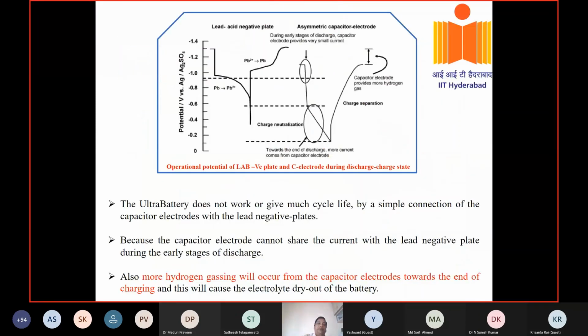But the problem is the current sharing between the capacitor electrode and the negative electrode of the lead-acid battery during the early stage of discharge. You see here the voltage profile. So how to make the capacitor electrode share the current with the negative electrode of the lead-acid battery during the early stage of discharge? That's very important. Also, a gassing reaction may occur at the capacitor electrode at the end of charging, which may also cause dry out of the battery. These things should be taken into account to make ultra batteries, so lead carbon and ultra batteries.